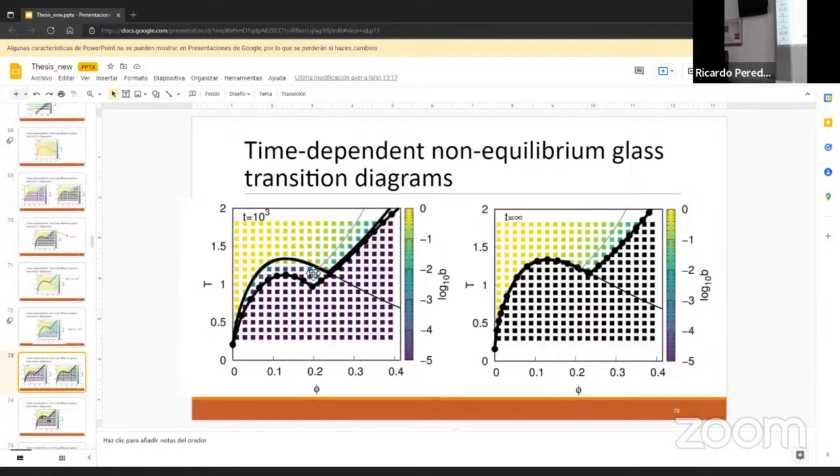But once it enters inside the spinodal line, because it is reaching an arrested state, it will end up converging to the spinodal line, and that's because of the intricacies of the evolution of the mobility, because what we actually expect is, for example, latency times to occur.